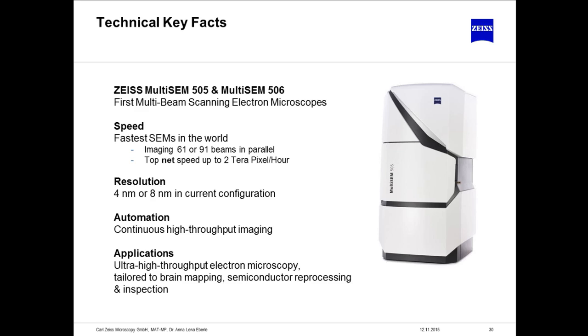So to just quickly sum up the technical key facts about these first multi-beam scanning electron microscopes in the world, the 61-beam version and the 91-beam version. The top net speed of the 91-beam version is about 2 terapixels per hour, or to say it in an easier way to grasp, a square millimeter can be imaged in a time frame of about 3 minutes with a 91-beam tool and maybe 5 to 10 minutes with a 61-beam tool, as compared to 2.5 hours with a standard single beam SEM.